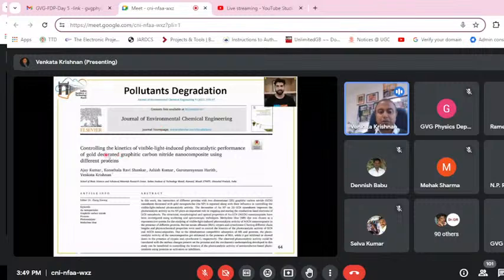In that work, we could control the kinetics of the visible light-induced photocatalytic performance of gold-decorated graphitic carbon nitride nanocomposites using different proteins. If you use certain proteins, the rate gets accelerated, whereas with some other proteins, the rate gets decelerated. So we can control the rate, basically controlling the kinetics of the photocatalytic activity.